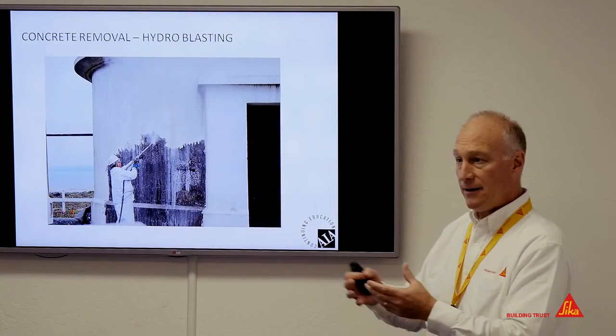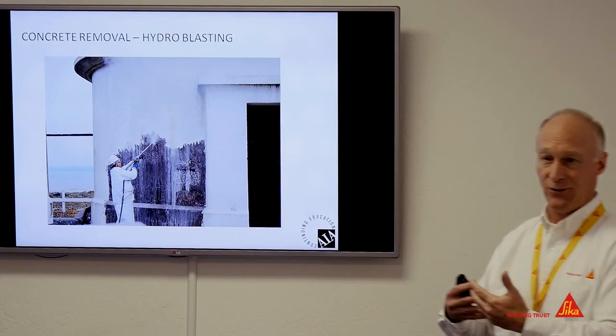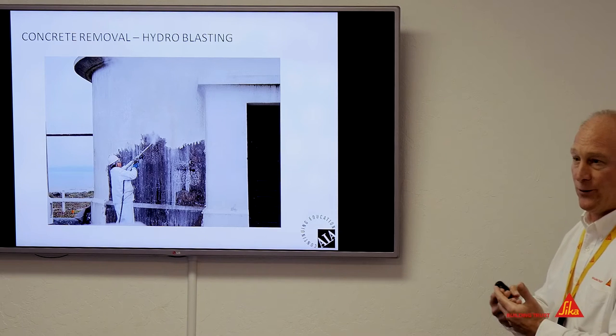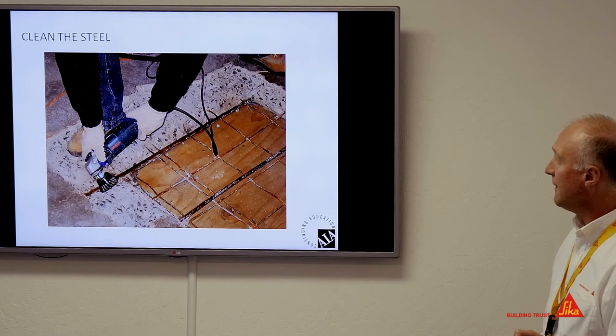But I've seen it done here in the Bay Area almost more than in other parts of the country. And as a supplier, I love it, because you don't bruise the concrete, you don't induce cracks, you clean it, and you get a very rough surface for concrete repair. You get beautiful adhesion. So it's a great technique.